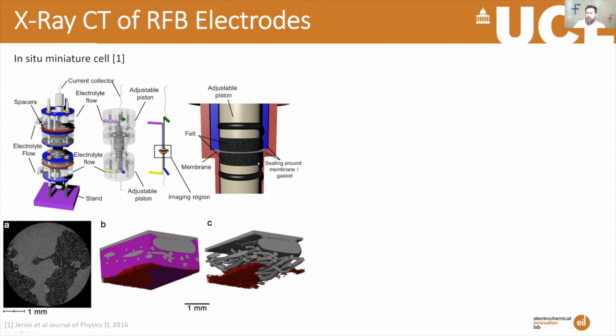We've got this sort of operando flow cell here where we can image the electrodes during flow and during charge and discharge. A lot of our studies actually found that the carbon electrodes are relatively stable over lots of charging regimes, and so we had hoped to just study a lot of degradation of these materials, but we didn't see a huge amount in a lot of what we've done. Nevertheless, you can see the flow characteristics, which is quite cool.